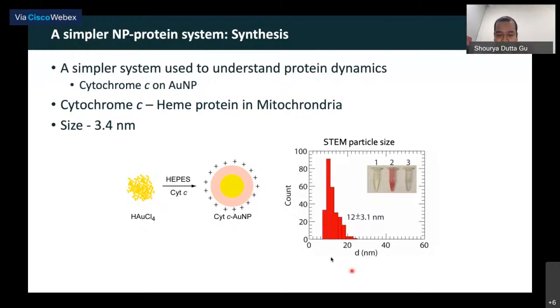So what we do is we do a simple nanoparticle synthesis where we reduce the gold salt using HEPES, which is a buffer, and add cytochrome C at the same time. So we get gold particles coated with cytochrome C. Now, this is a typical size distribution that we get. So this is the size, horizontal axis. Vertical axis is the histogram. And if you notice, we get nanoparticles of around 12 nanometers in size. And as I had mentioned before, small size gold particles have a typical red color, which is shown in this vial, which is the second one, right?